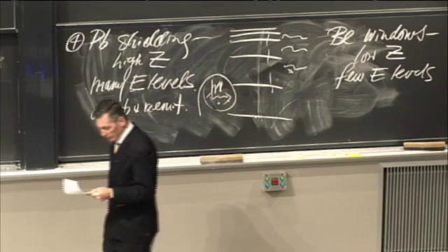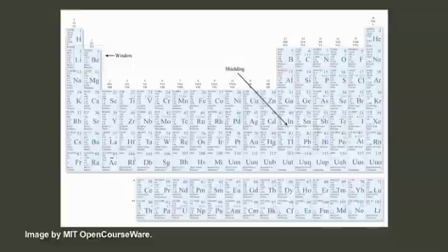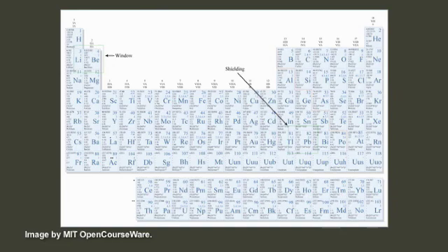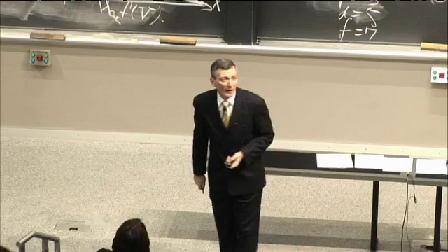While we're on the topic, he gave us lead shielding and beryllium windows. They were using silicate glass, but the silicate glass was absorbing some of the x-rays. To get higher efficiency, he chose beryllium. Why? It's got a low Z, so that means it has few energy levels. Therefore, there's less absorption and re-emission. Again, higher efficiency. This is the cathode here, the anode, and so on. The window is up here. You don't use lithium because lithium is unstable in air unless you had a giant room of humidity set at a dew point of minus 38 degrees C. Otherwise you use beryllium and lead down here. Why choose lead? You're pretty much at the bottom of the naturally occurring elements of the periodic table, so it's the cheapest of all these heavies.